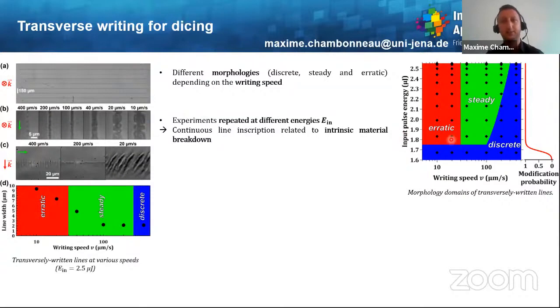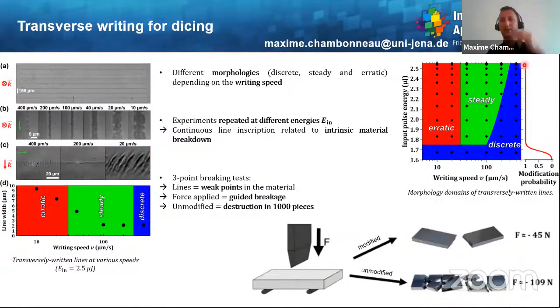And one can see that it is possible to write continuous lines transversely only when the modification probability is higher than 100%. Not higher, but equal to 100%, of course. This means that transverse line inscription inside silicon is intimately correlated with intrinsic breakdown and intrinsic damage production inside the material. And then my colleague Markus Blote has carried out recently some three-point breaking tests.